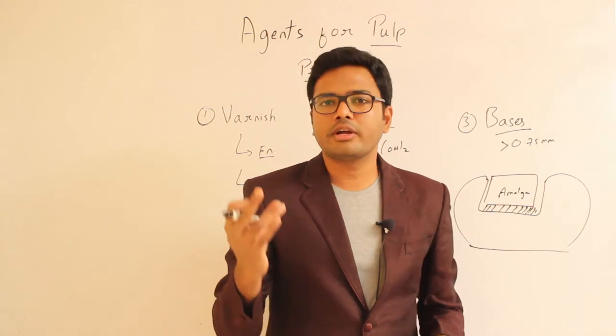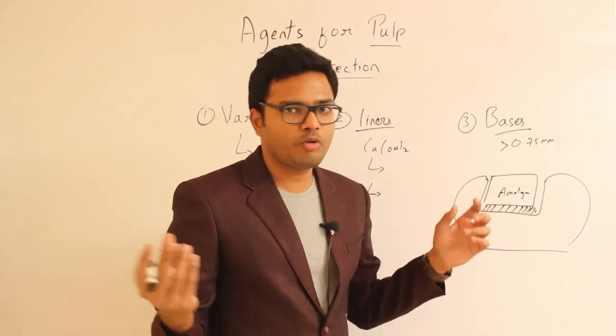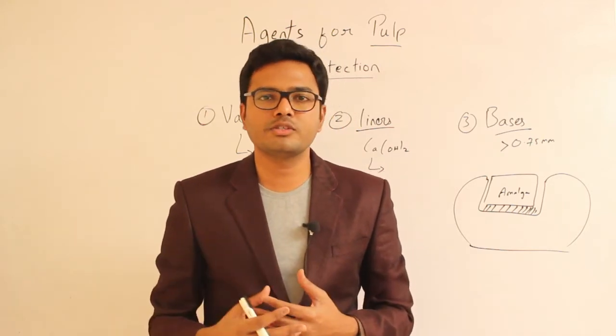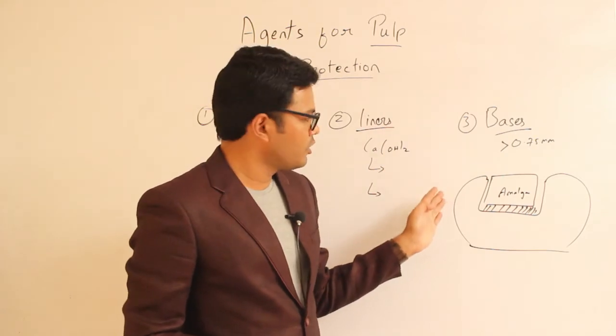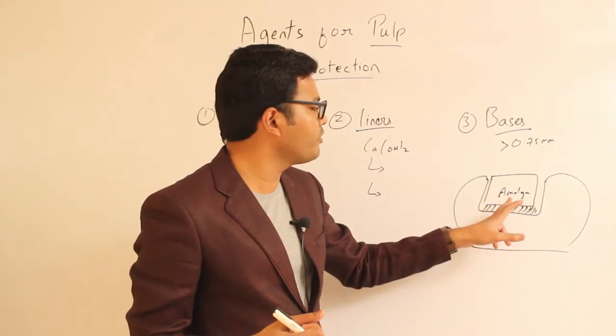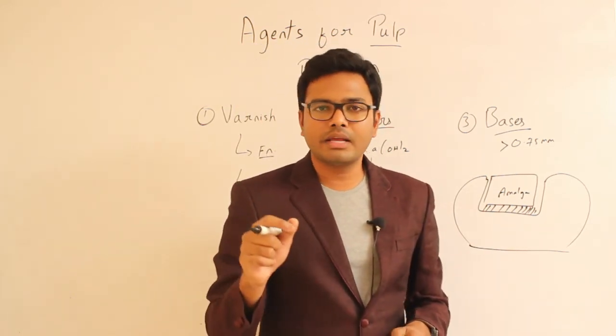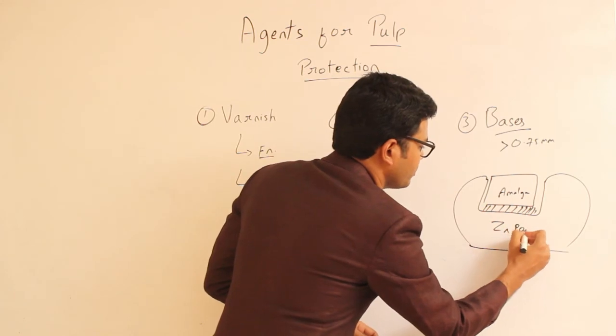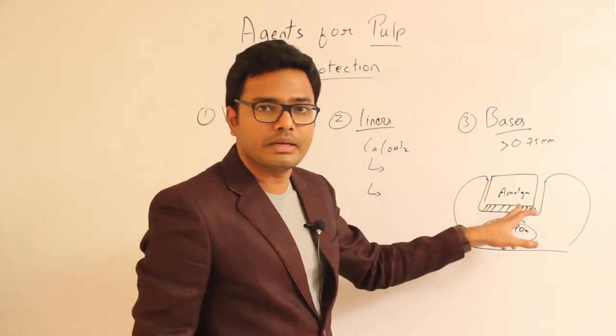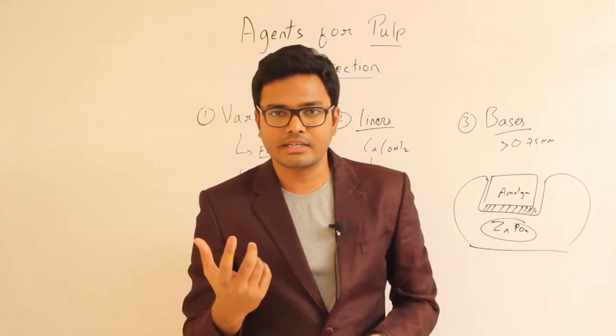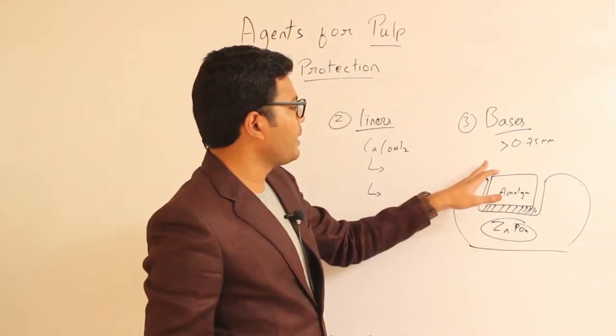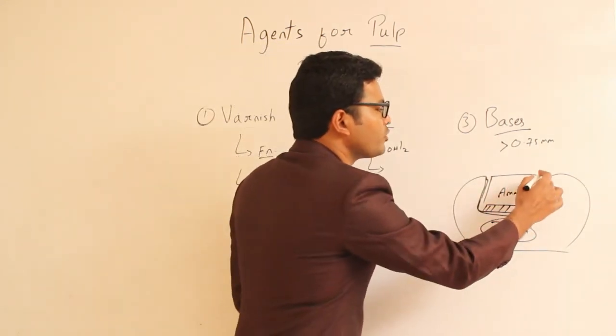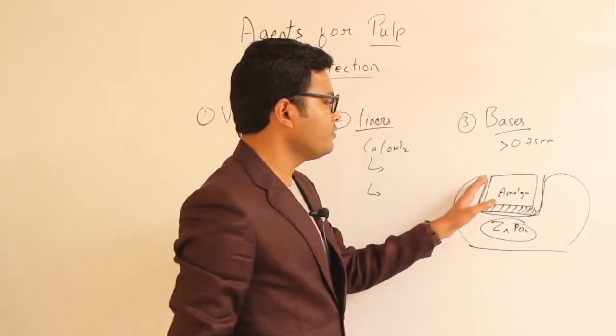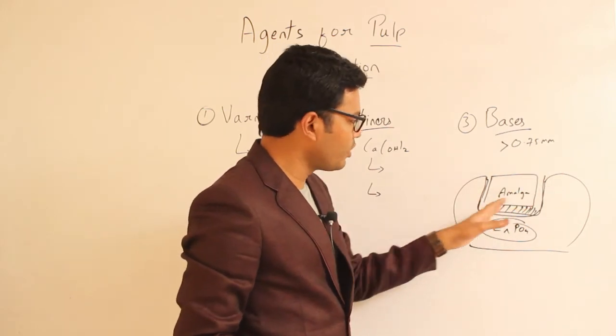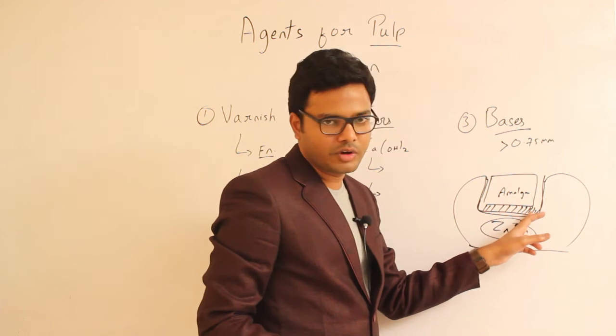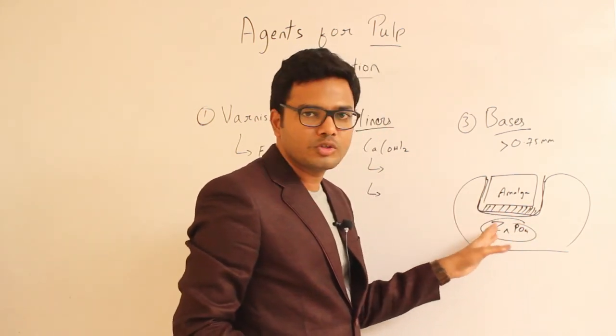So in this clinical scenario, when we are planning a class 1 amalgam restoration, we need to apply varnish, we need to apply base, and we need to restore it with amalgam. So what is the sequence of events we need to follow? Do we need to apply varnish first or base first? It all depends upon the type of base we are using. Suppose we are planning to place a zinc phosphate base, then since zinc phosphate is highly acidic, we can't directly place it on the dentin. We need to apply varnish first, because applying varnish seals the dentinal tubules, and then after applying varnish, we place a highly acidic cement such as zinc phosphate cement so that the chemical irritation to the pulp will be reduced.